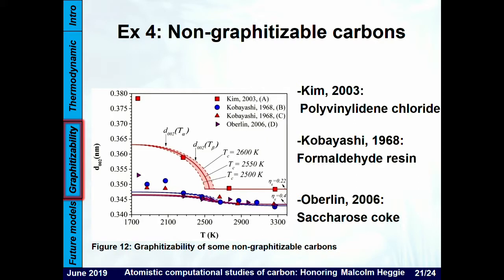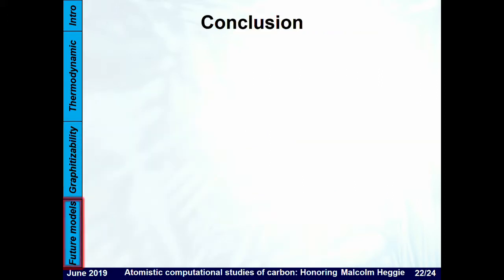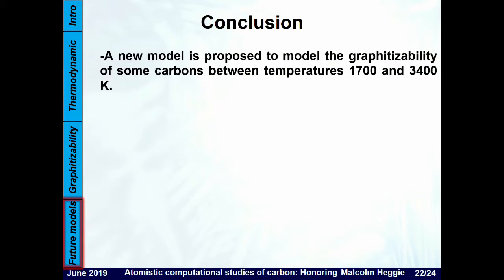Below this temperature, the graphitization process is usually still influenced by the release of heteroatoms such as sulfur or oxygen. Only at these high temperatures do the model and the experiment agree, because from then on, only carbon is involved in the graphitization process, and obviously right now the model is limited to pure carbon materials. So in conclusion, a new model was proposed to model the graphitizability of carbon between 1700 Kelvin and 3400 Kelvin.